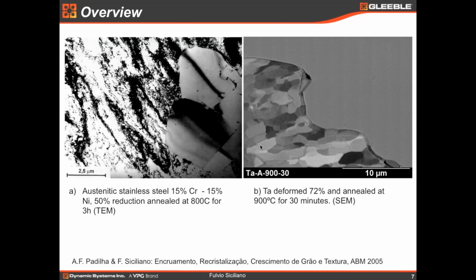Now let's come to real life. A couple of pictures. This is austenitic stainless steel, deformed 50% in reduction, and annealed at 800C for 3 hours. We can see here on the left side the work hardened microstructure, and all the dark areas are dislocations. And we have the recrystallized grains growing over the deformed part of the specimen. In other words, when this grain grows over this part of the microstructure, it will reduce the free energy because these dislocations will be eliminated.